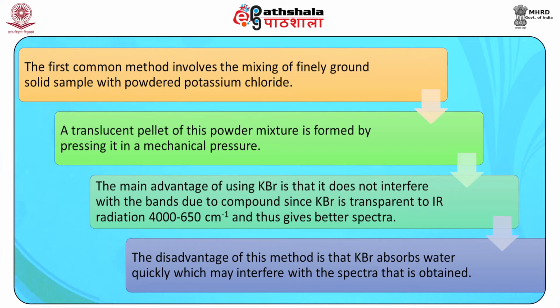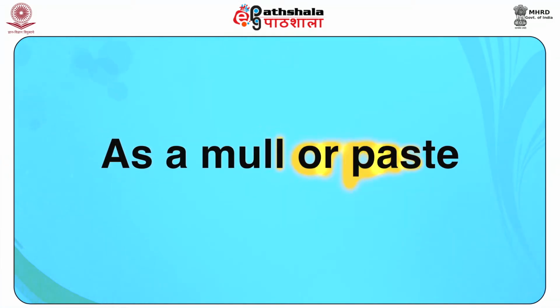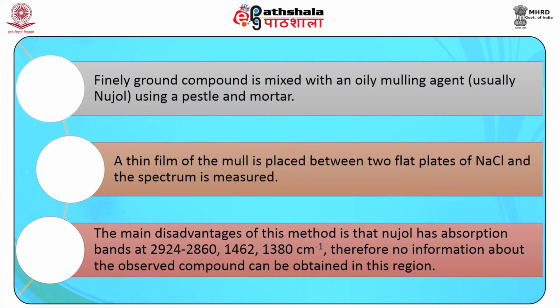The disadvantage of this method is that potassium bromide absorbs water very quickly, which may interfere with the spectra that is to be obtained. Now, the second method to obtain a solid sample is as a mull or a paste. Finely ground compound is mixed with an oily mulling agent, usually known as nujol, using a pestle and a mortar. A thin film of this mull is placed between two flat plates of sodium chloride and the spectrum is thus recorded. The main disadvantage of this method is that nujol has absorption bands at